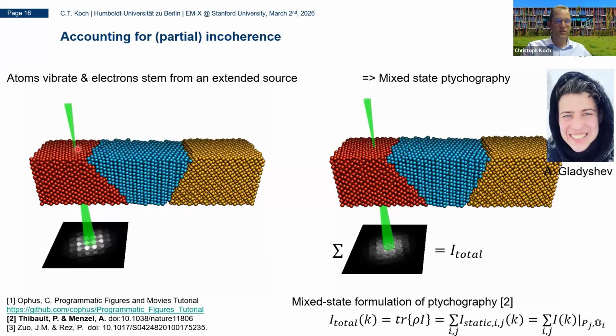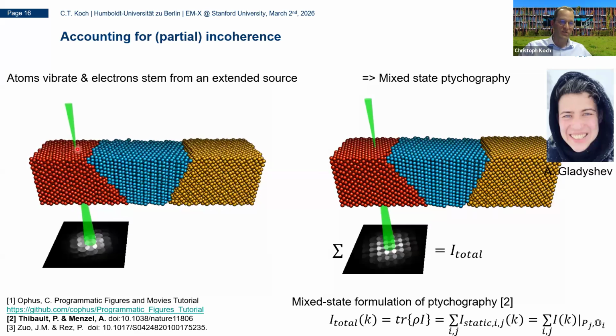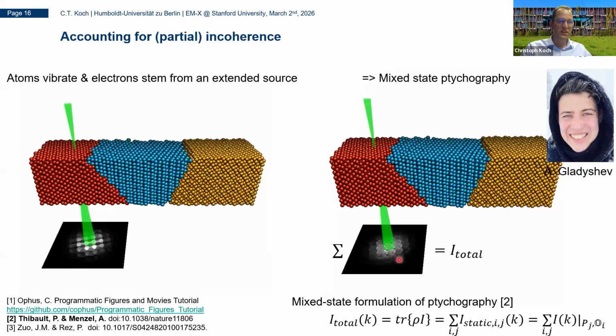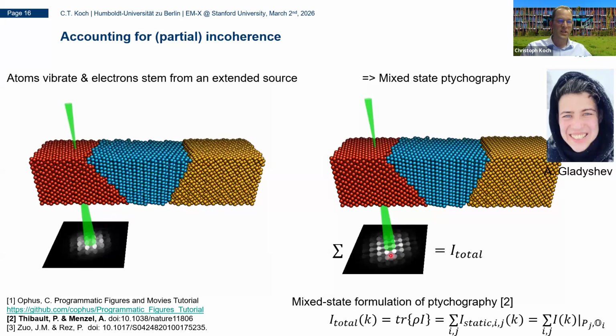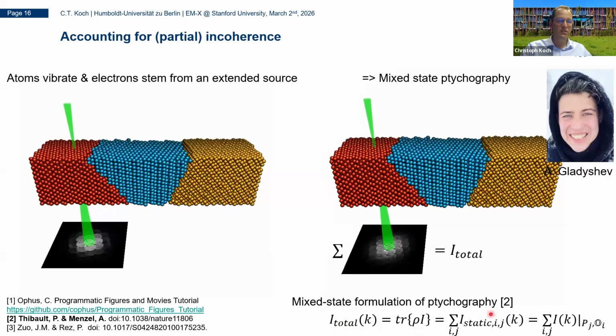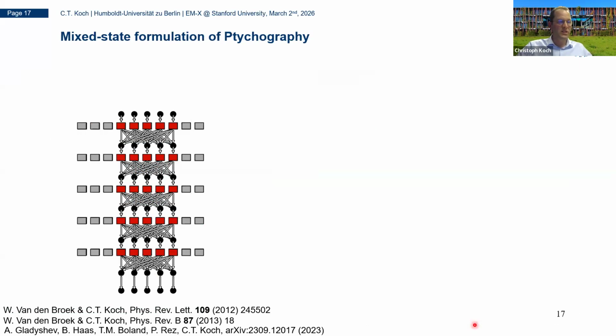And so you can do this in ptychography as well by doing exactly the same thing, only in reverse. So what you do is, instead of simulating only a single diffraction pattern for each probe position, you simulate the diffraction intensity by summing over all the static displacements and all the different probe modes in your beam. So let me show you how we do this. Since this work by Wouter van den Broek, who was a postdoc in my group but now works for Thermo Fisher, we've been using these artificial neural networks to represent the scattering of electrons.